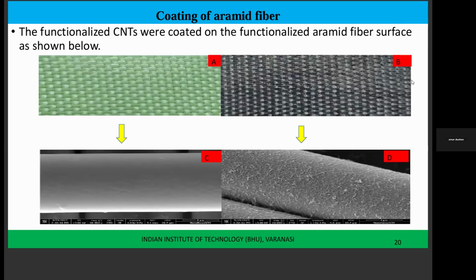So next one, functionalized CNT on the functionalized aramid fiber surface. Aramid fibers, you can see initially something like a green color contour, and when you look at the micro level in the SEM, you can see a very smooth surface of each fiber. For the functionalized one, you can see a change in the color contour, and a lot of roughness in the bottom image when we visualize in the scanning electron microscope. So it says that there is a kind of bonding and a kind of oxidation taking place, and you can expect enhanced properties.